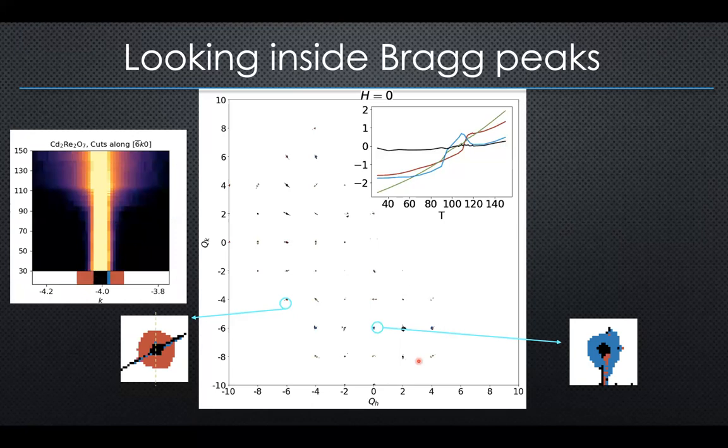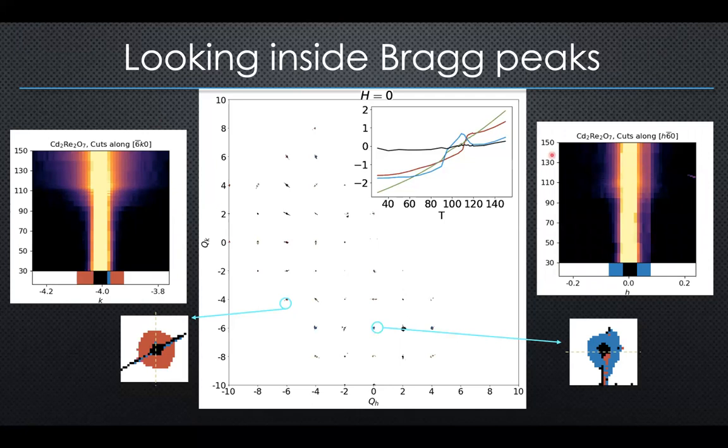And then we realized that, first of all, this is just what's in the data. We just make the line cut and you see literally, this is the diffraction region, and this is the diffuse region, that's called the fluctuation region. And what we realized is that this diffuse region is consistent with what a Goldstone mode associated with this two-dimensional order parameter would do. So this ordering into the two-dimensional order parameter phase was like ordering in an XY model. There was a little bit of anisotropy, but like in an XY model, you order, you still have a Goldstone mode.